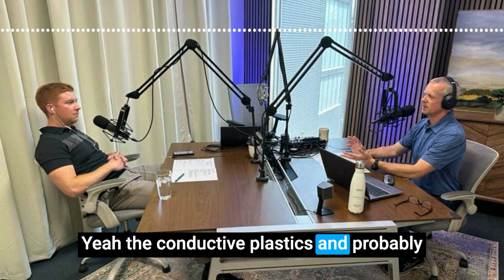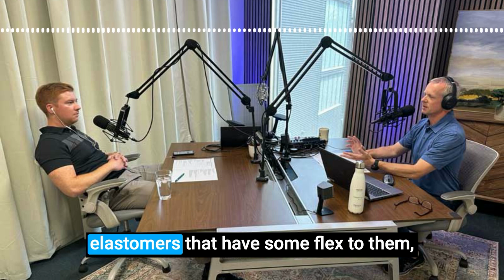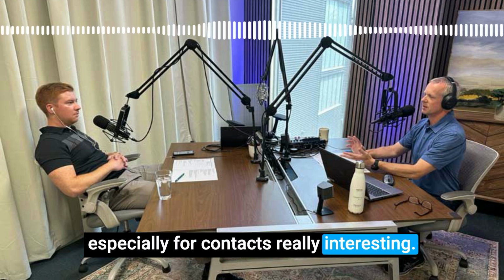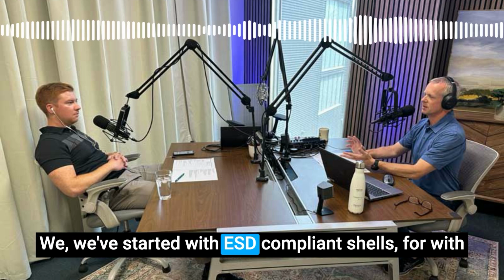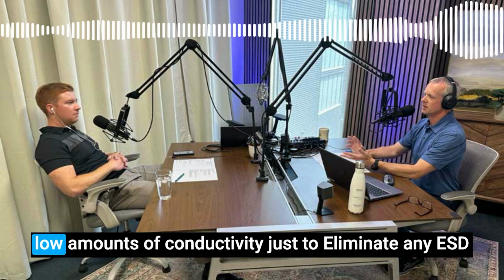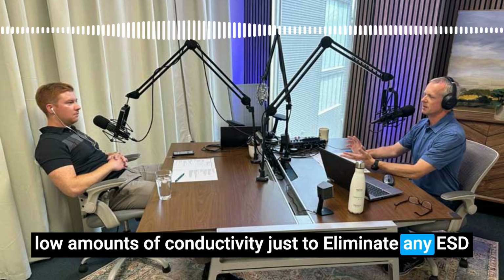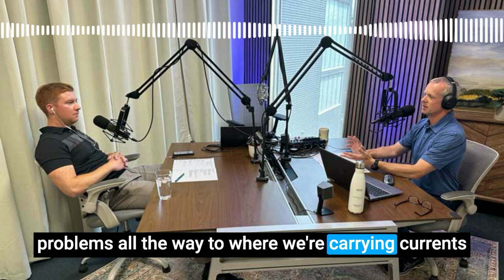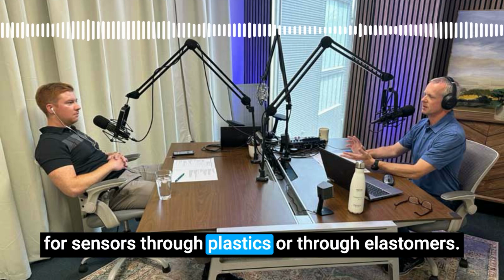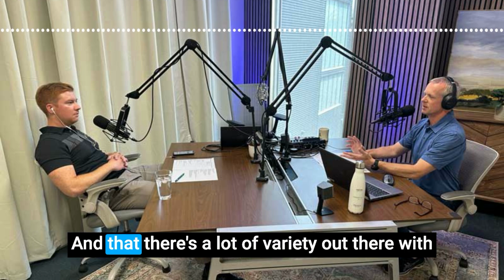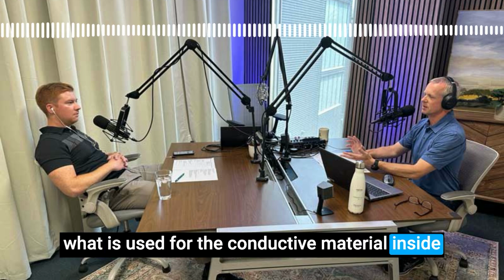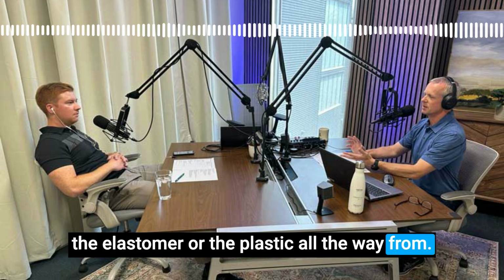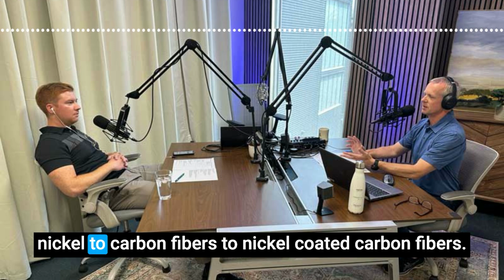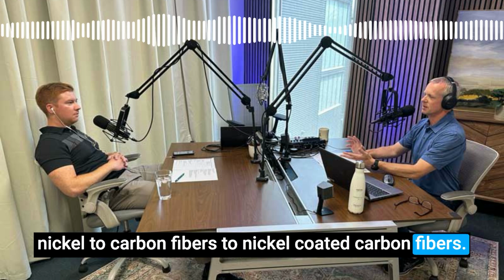Yeah, the conductive plastics, and probably more interesting the conductive elastomers that have some flex to them, especially for contacts. Really interesting. We've started with ESD compliant shells with low amounts of conductivity just to eliminate any ESD problems, all the way to where we're carrying currents for sensors through plastics or through elastomers. And there's a lot of variety out there in what is used for the conductive material inside the elastomer or the plastic, all the way from nickel to carbon fibers to nickel-coated carbon fibers.